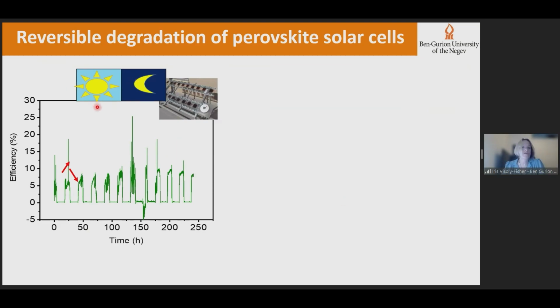Another aspect of that is that we can look at the differences between nighttime and daytime. Apparently, perovskites have a very unusual property where they change their efficiency as a function of time. What you can see here is measurements of the efficiency as a function of several hundreds hours outdoor, where we follow the efficiency as a function of time. This would be the days, and this would be the nights. And what you can see is the efficiency consistently increases during the day under illumination, and then decreases from here to here, or from here to here, or from here to here during the nighttime. These kind of reversible processes are very unique to the perovskite photovoltaic technology, and we have the power to test it because we can observe the differences between light cycles and dark cycles.